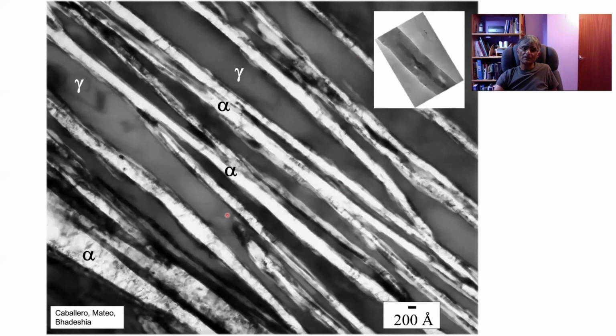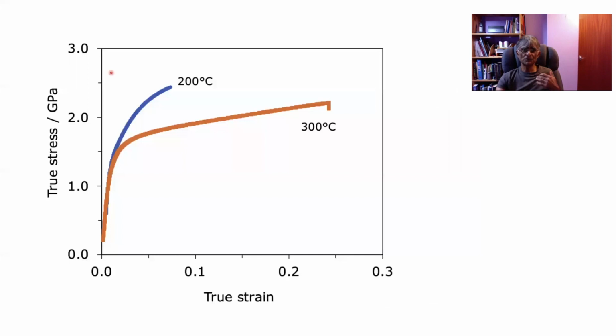It's remarkable, actually. Now, you may argue that, okay, these are long, but the mean free slip distance in a plate is twice the thickness. If you do a stereological analysis for the mean free slip distance, because slip in the plane of the plate is very unlikely, then it's twice the thickness. So we've achieved an incredibly fine grain size purely by phase transformation, which has an isotropic structure, and there's no rapid cooling involved in this process, so you don't have the distortion. And sure enough, you get work hardening, and depending on your transformation temperature, you can control the strength. This is about 2 gigapascals and about 25%, let's say 22% elongation.